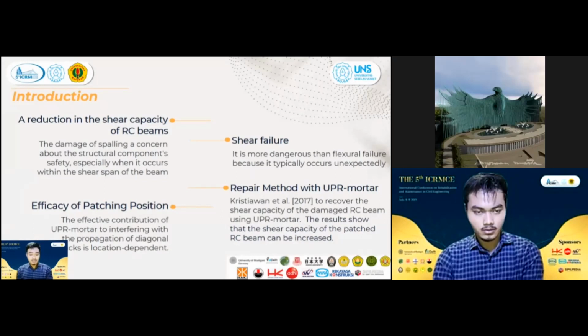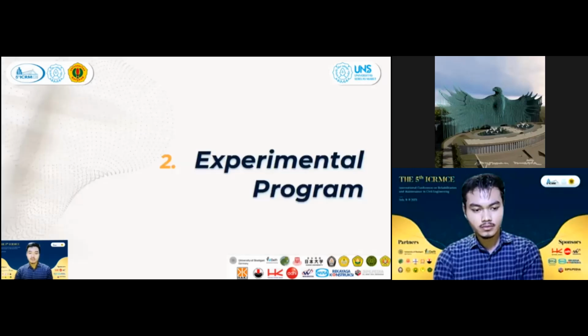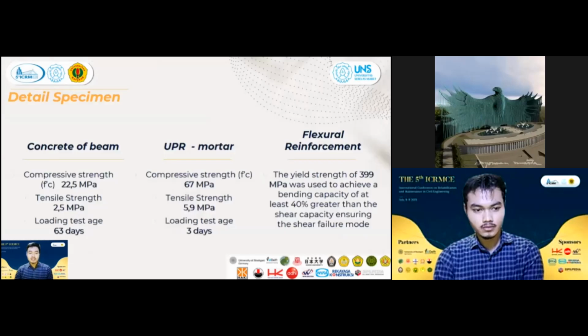Kristiawan et al. 2017 recovered the shear capacity of the damaged RC beams using UPR mortar. The research showed that the shear capacity of the patch RC beams can be increased. Furthermore, the effective contribution of UPR mortar to interfering with the propagation of diagonal cracks is location dependent. Next, experimental program. The beams were made of ordinary concrete with material specification as follows.